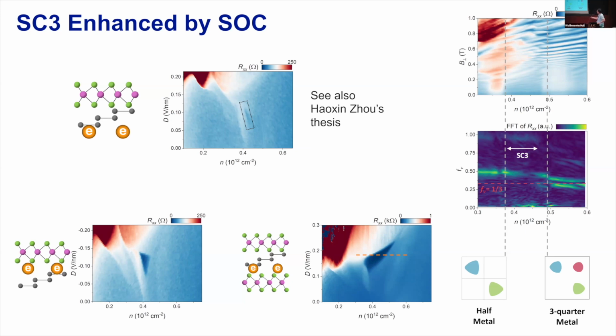And what's different now is that if you push the electrons to the layers right next to the TMD, so they can experience somewhat weak spin-orbit coupling, you now have a region roughly at the same place as these dips that shows resistance down to 0. And if you make the spin-orbit coupling stronger, this region showing superconductivity becomes bigger, although it doesn't look exactly the same shape, but it is expanding. So we think this is a state of superconductivity that got enhanced by spin-orbit coupling a lot.